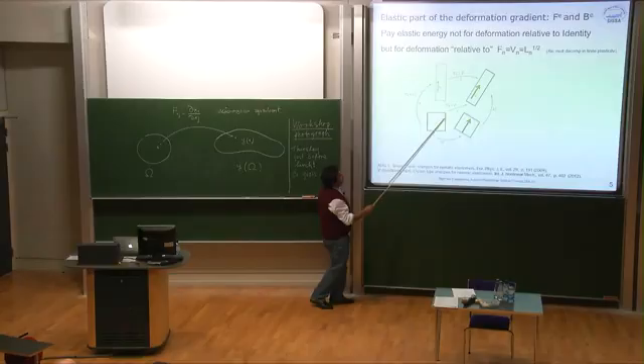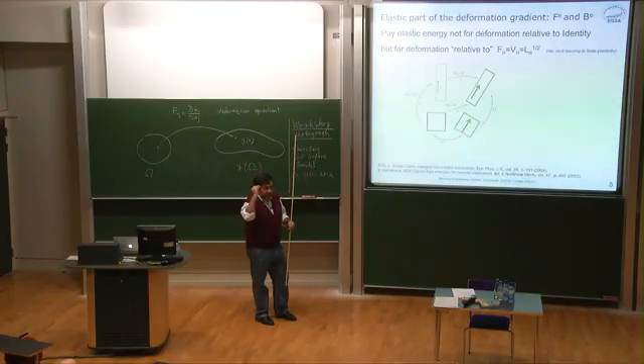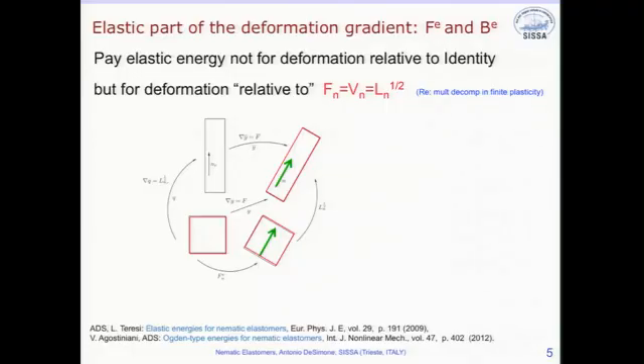So in our case, the preferred state is set by the nematic director. Okay? So we take an arbitrary deformation. Let's focus on the red part here. We take an arbitrary deformation, and there is a nematic director. The nematic director carries a coupling with elasticity. Now, thought experiment, I switch off a switch, and I turn off the coupling between elasticity and director. So that spontaneous deformation is recovered. And I know what that spontaneous deformation is because I told you yesterday, so I produce this. And so this is the part that is due to the coupling, and the leftover part, this one, is the part that stores elastic energy. Okay? So this is the way of constructing this. So any deformation gets multiplicatively decomposed into a part that is spontaneous and a part that stores elastic energy.